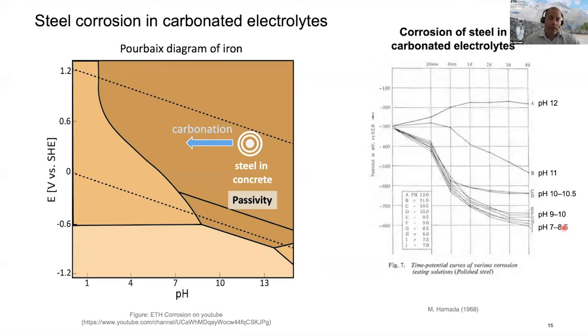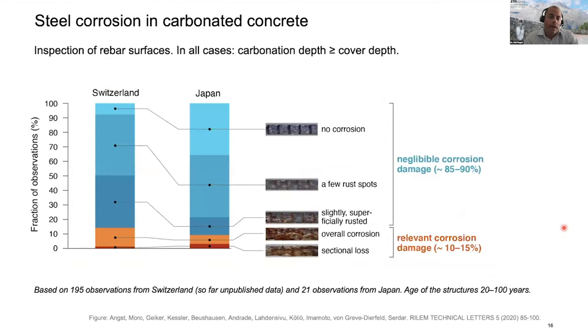So we were wondering, again, in another RILEM Technical Committee, if this also is the case in concrete, and we looked at data from inspections of real structures, and all the structures that we considered in the evaluation were structures where the carbonation depth had exceeded the cover depth, which means that the steel that was inspected had been in carbonated concrete for quite some time at the time of inspection. Despite this, the majority of those structures did not really show significant corrosion damage.